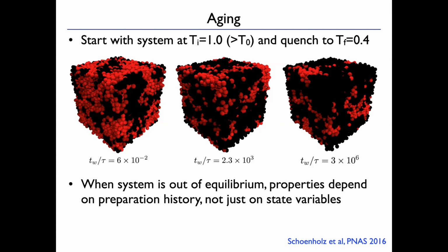So what I'm showing you is the softness of the particles. So red and opaque is high positive softness, black and transparent is high negative softness, okay? And what you see is over time, this system becomes darker and darker. The average softness decreases as the system ages, as you wait, okay? So this is the waiting time after the quench.